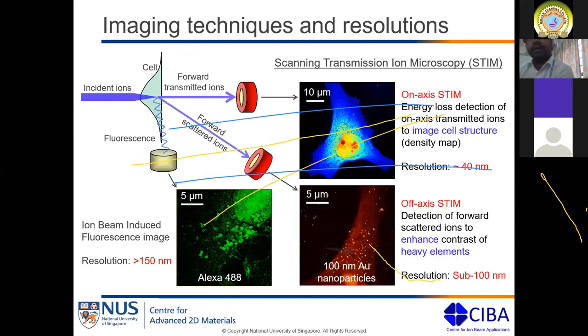So if you look at these slides, it shows how we can use STIM or scanning transmission ion microscopy to image cells, basically, right? So this is a cell image which is taken using a fluorescence detector. When ions hit the sample, then you get fluorescence out of the cell, and then you record the image of the cell inside a chamber, right?